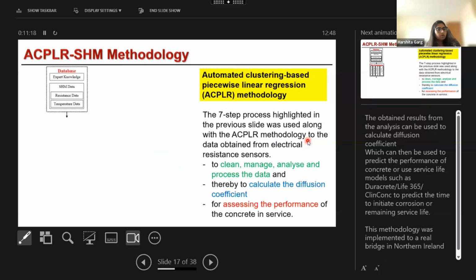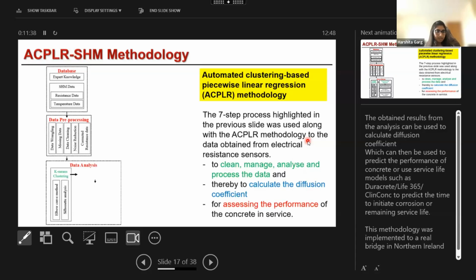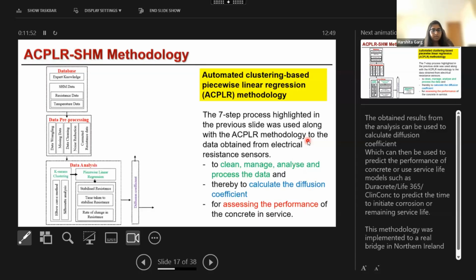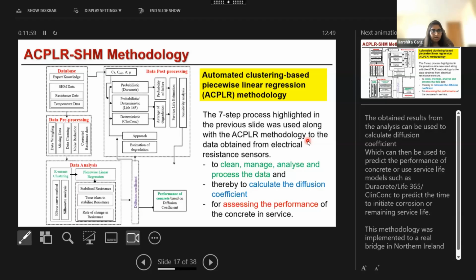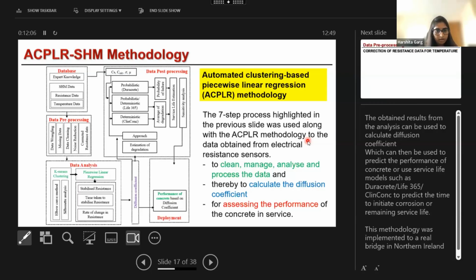The first step is to collect all the sensor data: resistance, temperature, and ambient conditions. Second is to clean the data, pre-process it, reduce noise, and identify missing information, so basically identify the general trends in the data. Then third is to quantitatively analyze the data using two algorithms called k-means clustering and segmented regression. The results from these two algorithms can be used to calculate the diffusion coefficient that is enough to assess the performance of concrete and structures. It can also be used in any service life model like Duracrete, Life 365 or ClinConc to predict the remaining service life of the concrete.